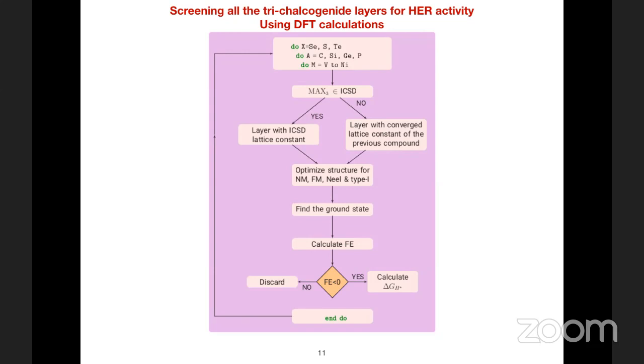And then we calculate the formation energy of that material in that configuration with respect to the isolated elemental solid phases. If the formation energy happens to be less than 0, that indicates that the material is thermodynamically stable. If it is not, it is discarded. And if it is found to be stable, then we adsorb hydrogen at various sites on this layer and calculate delta GH, and so on. It goes for all the 72 compounds, and the point here is that it is all done in one go. So it's not like you do calculations for 288 different situations. You just submit one job and you get your results in the end.